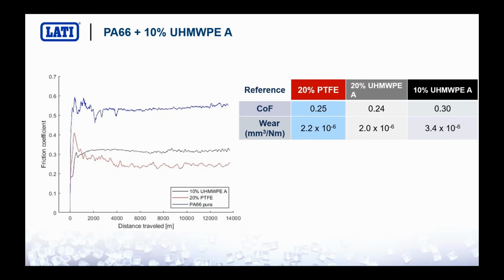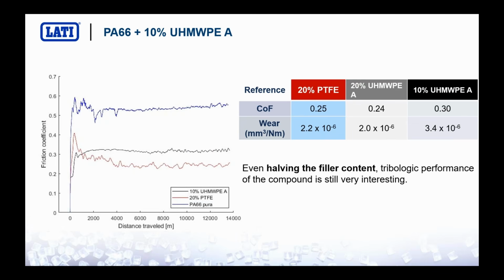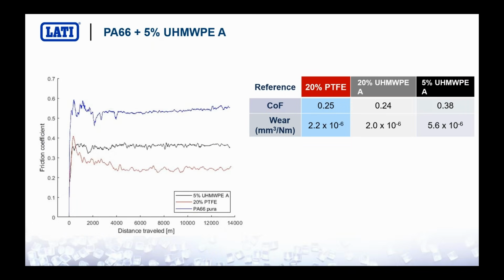Then we tried also to halve the percentage of 10% of ultra-high molecular weight polyethylene because, due to the fact that it's a polyolefin, it reduces the thermal properties of the base resin. So we tried to halve it in order to check if also with 5% we can reach good results. And the answer was yes. The results were still good because the friction coefficient was quite low, 0.3, and also the wear factor remained at a very good level. So also this compound is very, very interesting.